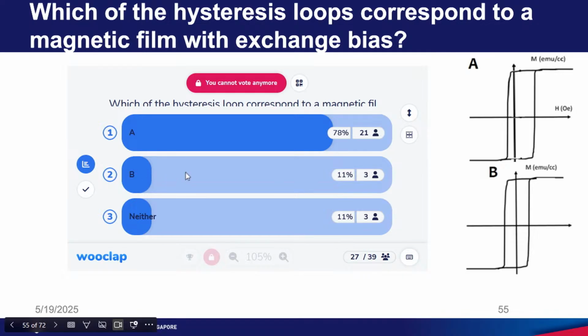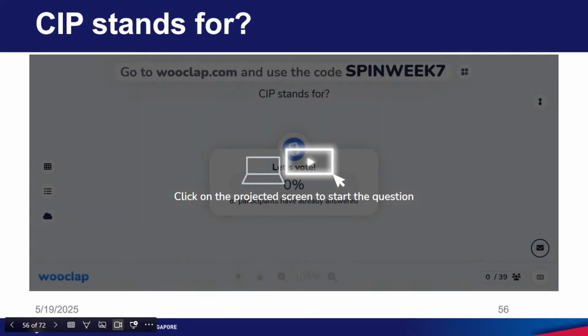Okay, I am totally disappointed with this answer. The loop B is very symmetric, so there is no reason to say that it has exchange bias. Loop A has shifted, so it has shift. So there is exchange bias. In this case, the exchange bias is smaller than the coercivity.